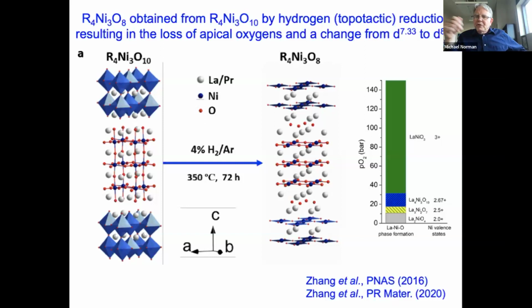This phase diagram gets pushed to higher oxygen partial pressure when you go from lanthanum to praseodymium to neodymium, which is why things are always easy to make in lanthanum and become harder to make as you go from lanthanum to praseodymium to neodymium.